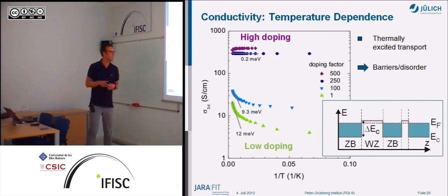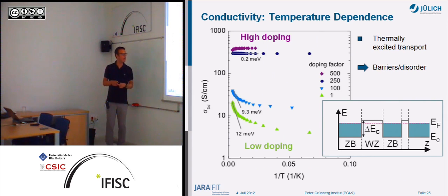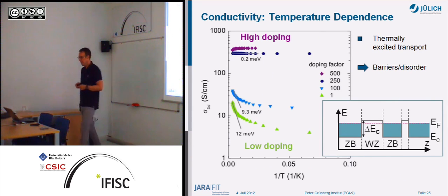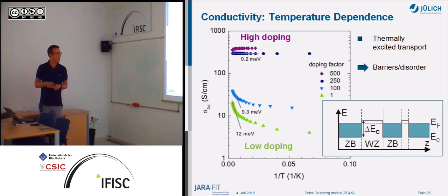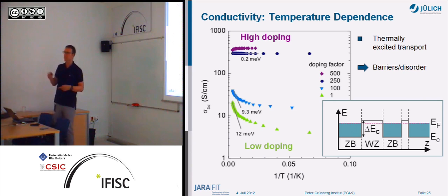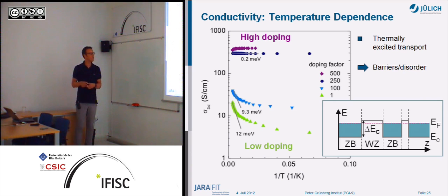What I said is that you also have different band structures, so different crystal orientations. You have zinc blende and wurtzite structures here. And if you look at the band gap, you see that the wurtzite structure has a slightly larger band gap. So if you look along the nanowires, what you expect is that you have some steps in the potential which somehow influences the transport here. That's what you see here as well.